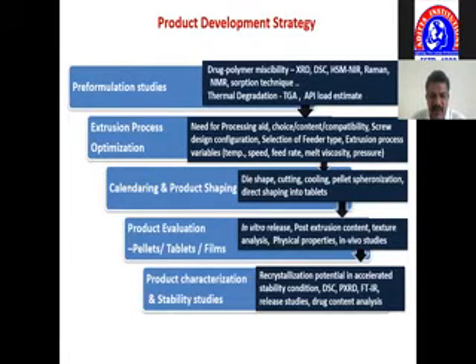Once the pre-formulation study has been done, you need to go for an extrusion process. In hot melt extrusion process, there are four major parameters which you need to work on. One is screw speed, which is the RPM of the screw which is running. Second is going to be the barrel temperature, what temperature you are going to be using to melt the polymer or the drug combination. Third is going to be the feed rate, how much of material you are going to be putting inside the barrel. And fourth is going to be the screw configuration.